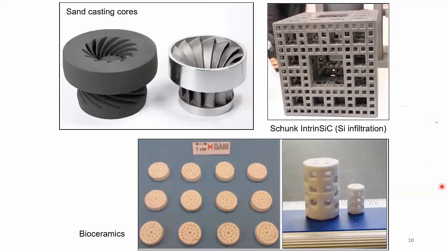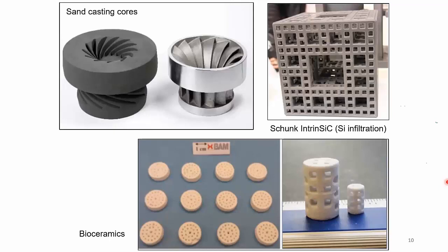You can see some examples of casting cores made with this technology. Companies like Schunk are generating components based on silicon carbide. After sintering with this approach, it is very difficult to achieve full density, but you can infiltrate with molten silicon to produce a high-performance, fully dense component — for instance, a heat exchanger. You can see the degree of shape freedom afforded by additive manufacturing. People are also working with this approach to fabricate bioceramics, where residual porosity is not detrimental but actually beneficial, because it improves the possibility of attaching cells to the scaffolds.